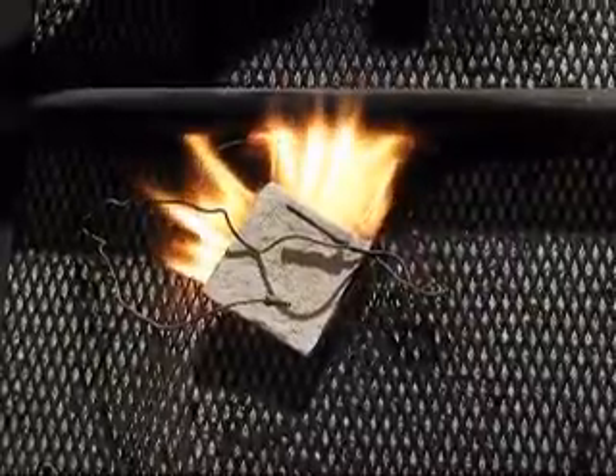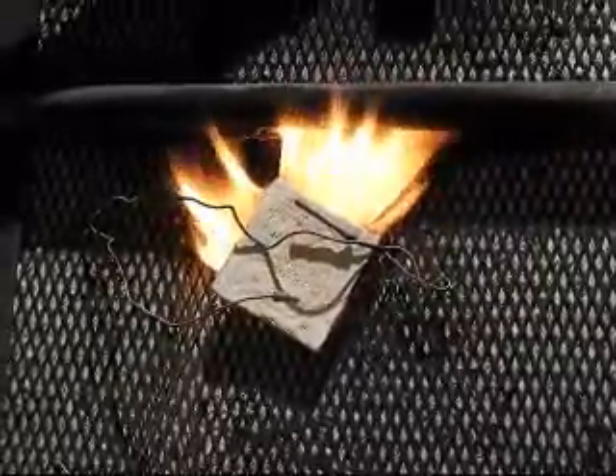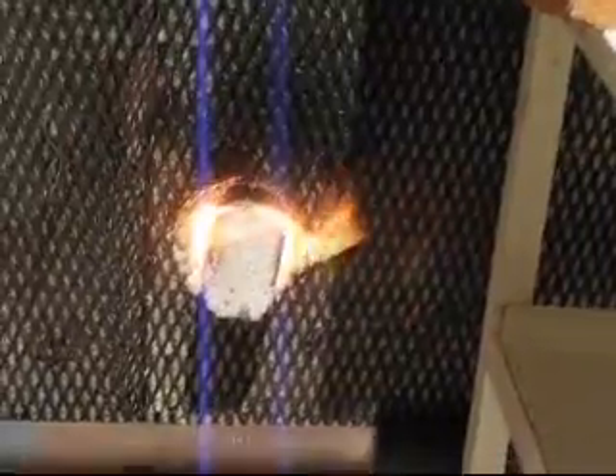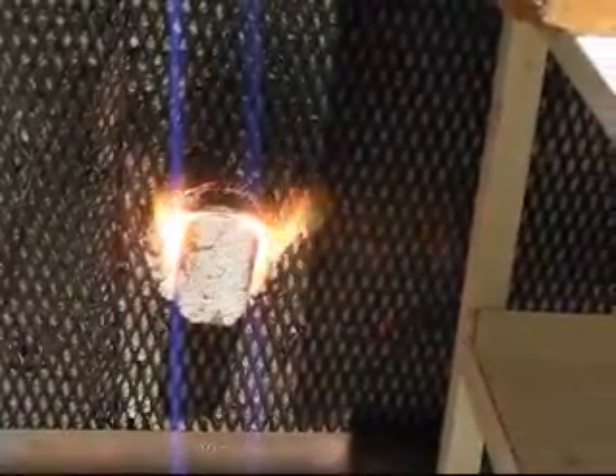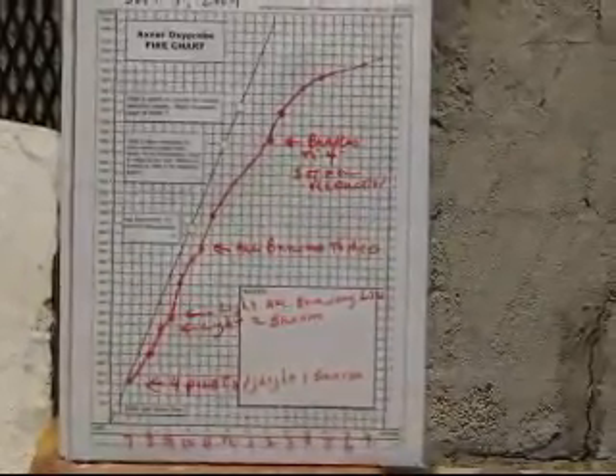It's now 7:45 in the evening, and that's the top burner, top spy hole, and bottom spy hole. So I have maybe a little too much back pressure, but I'm reading 0.7 on the oxyprobe, so I know my reduction is about right. However, my temperature has slowed down, so I'm only at 12.8, and you can see how flattened out the curve is becoming. So I have a choice.